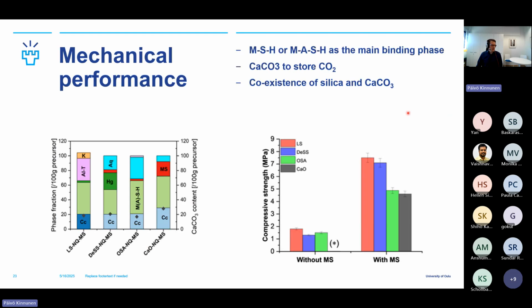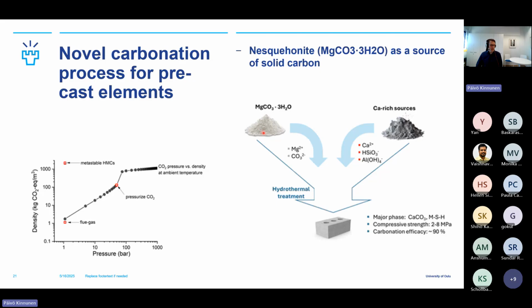And just to go back to the beginning, when you do that, you're combining a solid carbonate and solid raw materials. So you can get those well mixed in the beginning, and the reactions are happening inside your brick, and if you compare this to carbonation processes, it's much simpler. You don't have to care about the humidity level or carbon dioxide level. If you're doing calcium carbonation, you have to control those variables really well. And if you're starting from flue gases, your carbonation is going to take probably days, and you're not going to get 100% carbonation. But here we can use just simple industrial autoclaves.